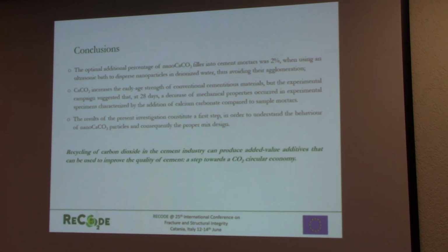The first very little conclusions up to now are that probably the optimal addition of this kind of particles is set at 2% with respect to the weight of cement. The ultrasonic bath is fundamental to guarantee a proper dispersion. Probably, and this will be investigated with the help of applied science and technology, these particles, for their morphology and for their chemical composition, increase the early age strength of cementitious materials.